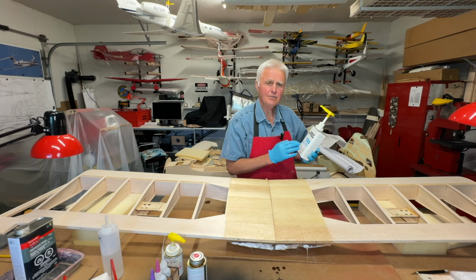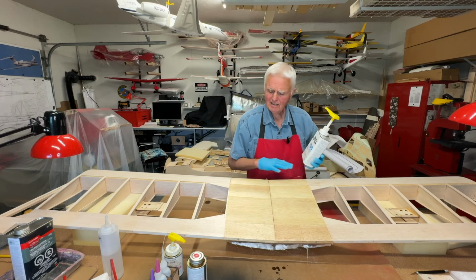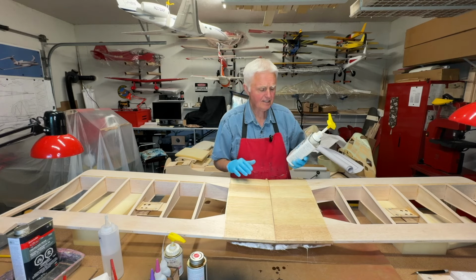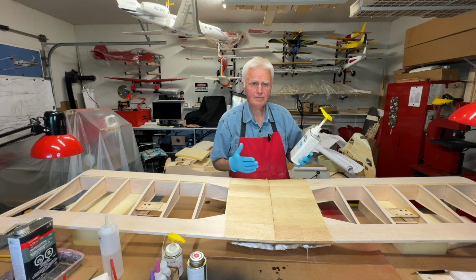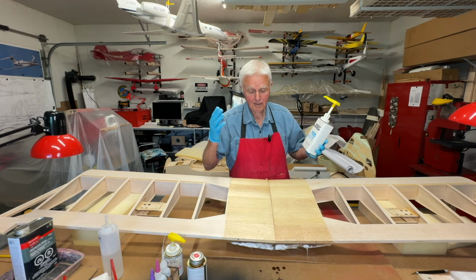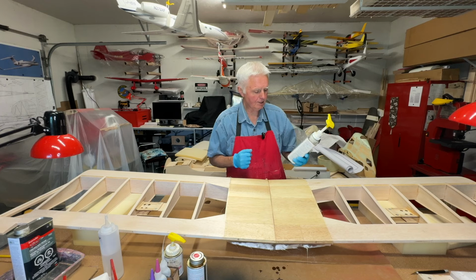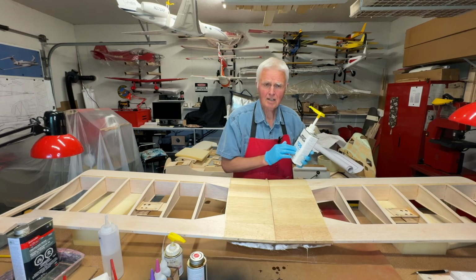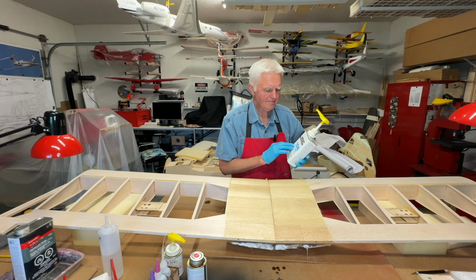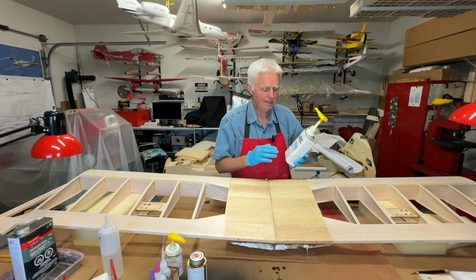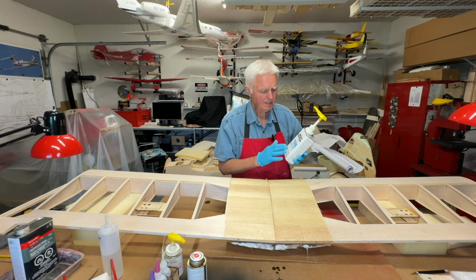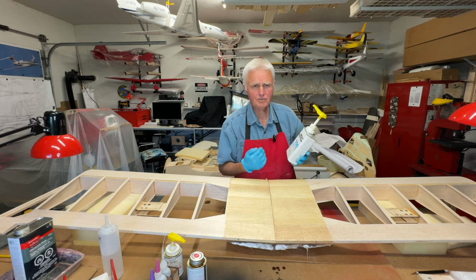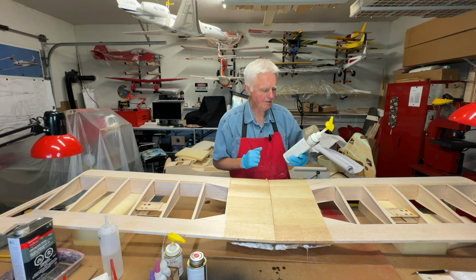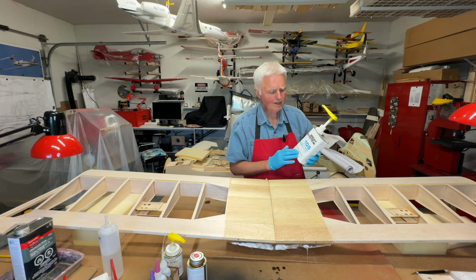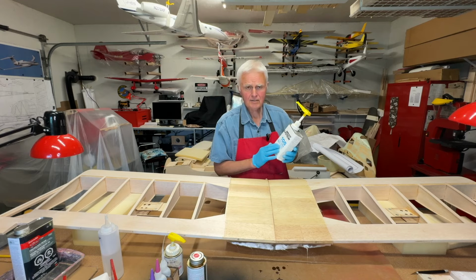The reason I like using epoxy resin, and particularly West System, is that it levels off nicely, it sands easily, and is extremely strong. As a matter of fact, if you build model boats, it's even waterproof. It can be used below the waterline. The other thing I like about epoxy resin versus fiberglass resin, particularly when I make fiberglass cowlings, is that it's more flexible and it's also easy to repair. So if you epoxy something and you're going to fix it, just use epoxy resin and it works very well. Although I will have to say, West System epoxy resin is rather expensive.